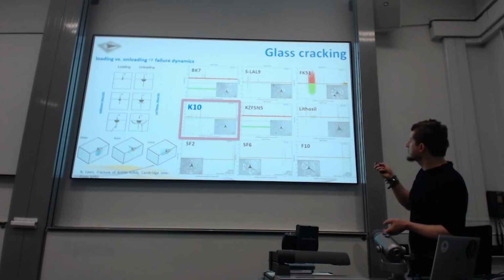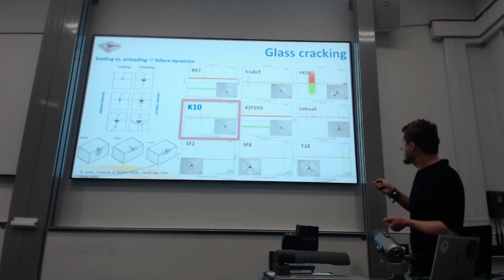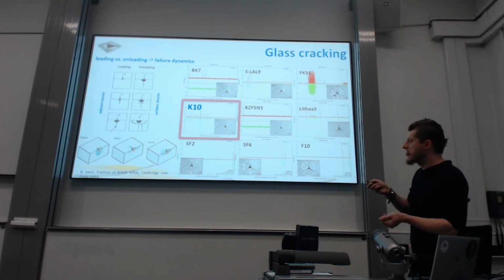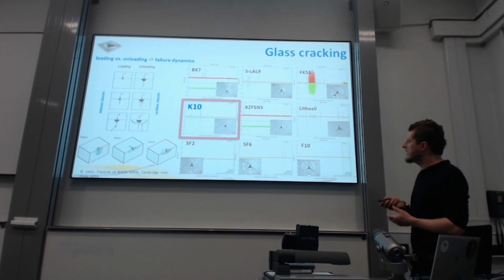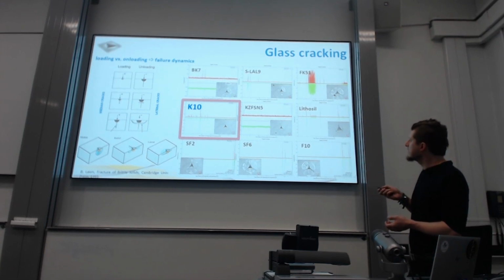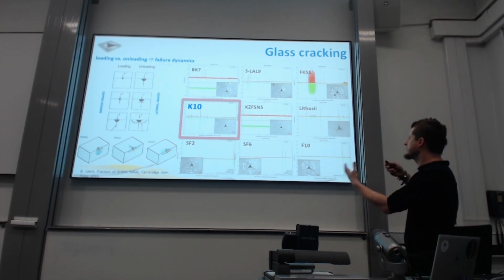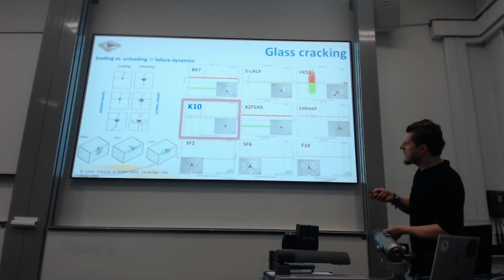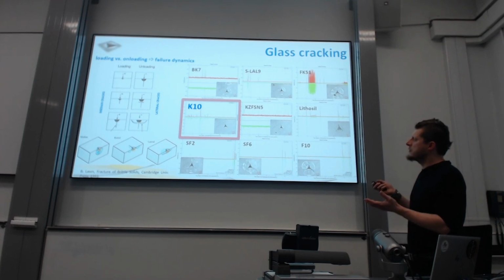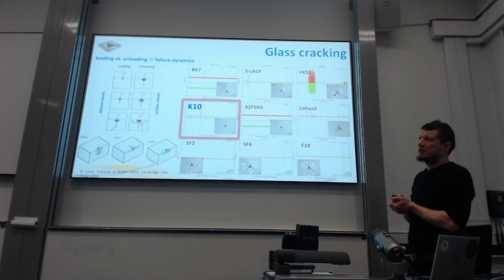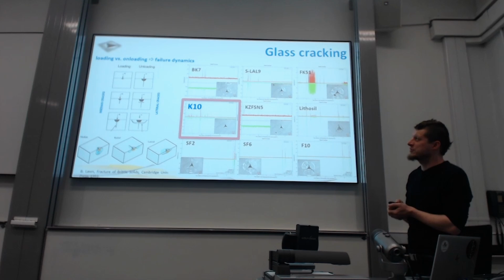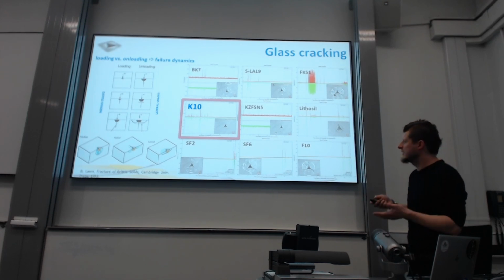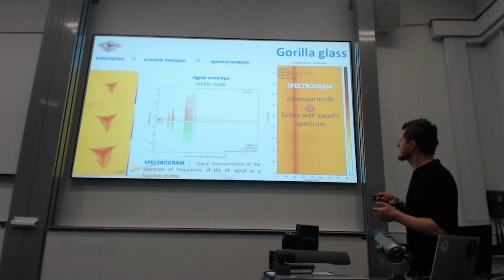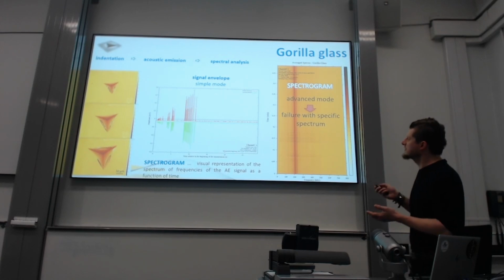This glass actually created an acoustic burst and a lot of acoustic emission during unloading. So probably lateral cracking, and here also. So it can give you nice information, even if it doesn't look so distinguishable. Several times we have made measurements for Sisecam, a big Turkish company that creates something like Gorilla Glass. So we also tested this Gorilla Glass.